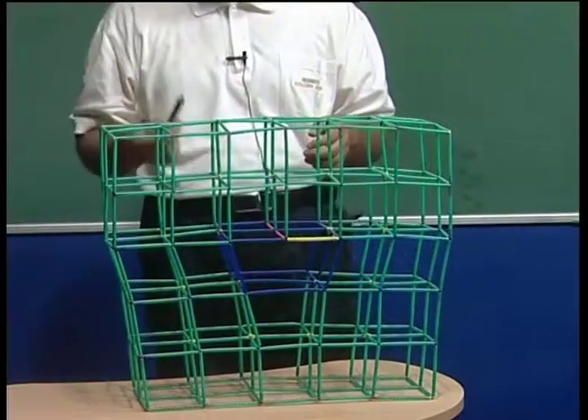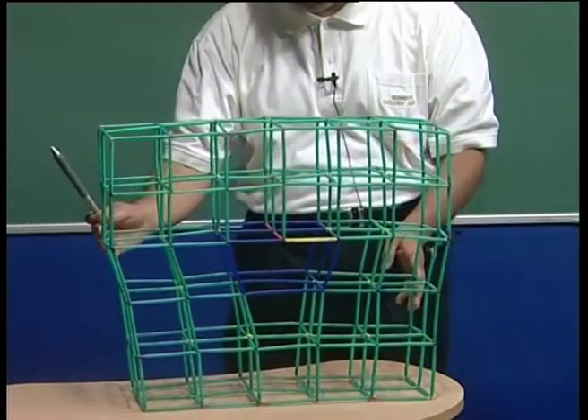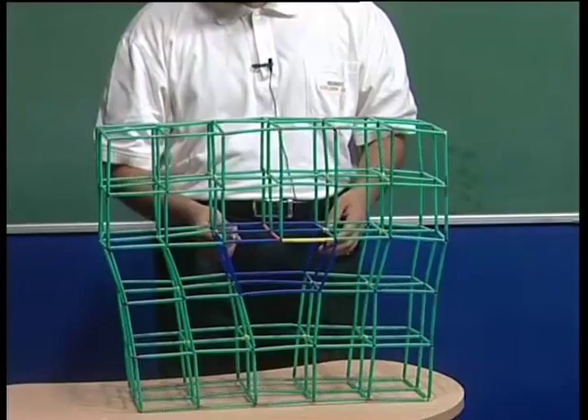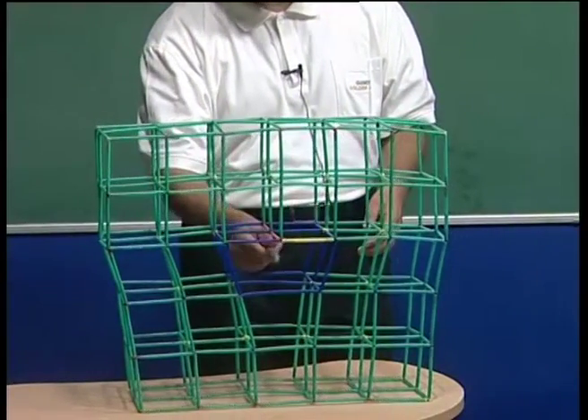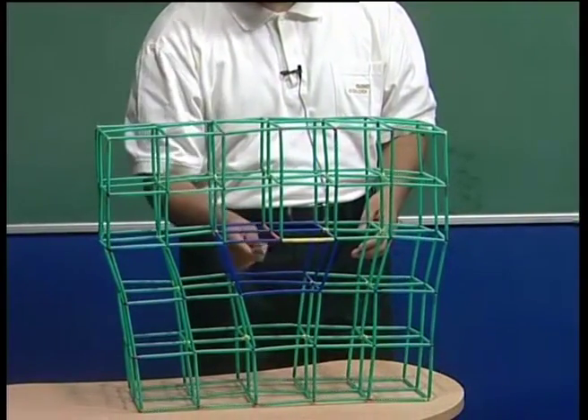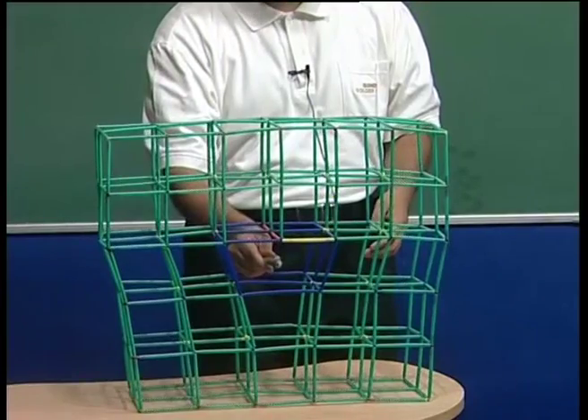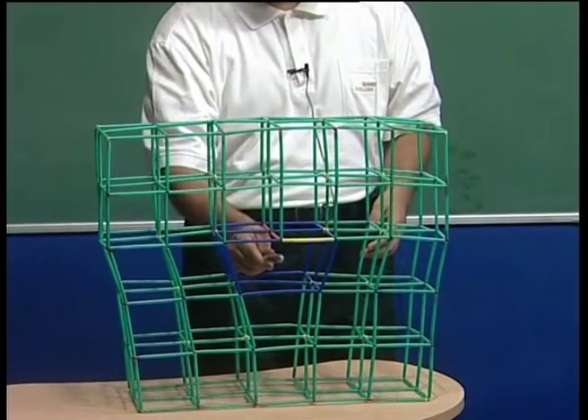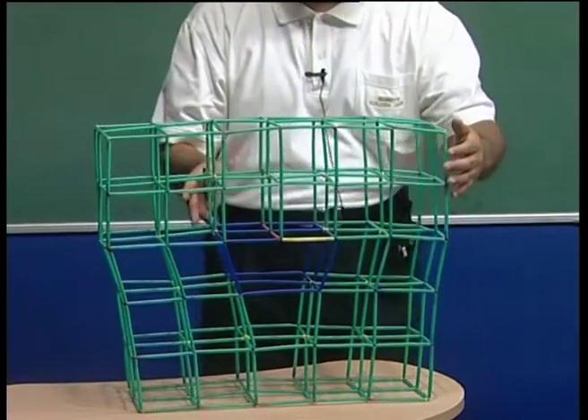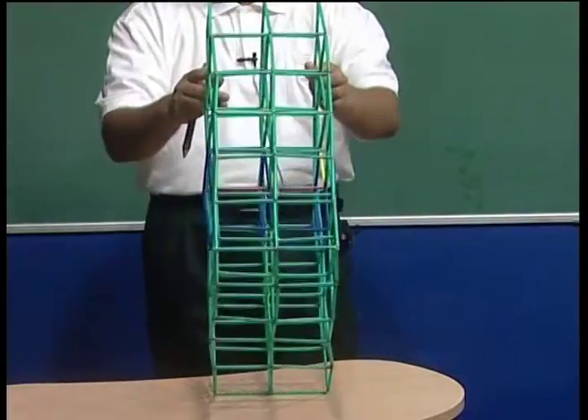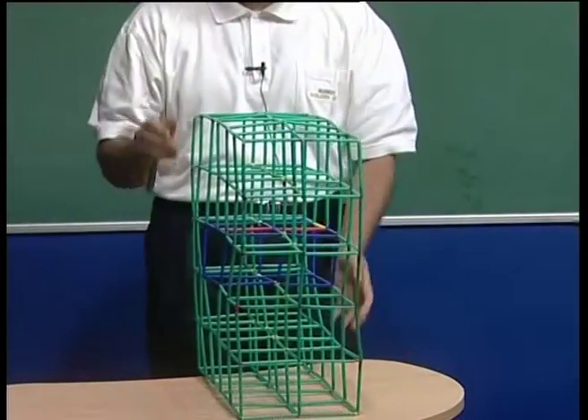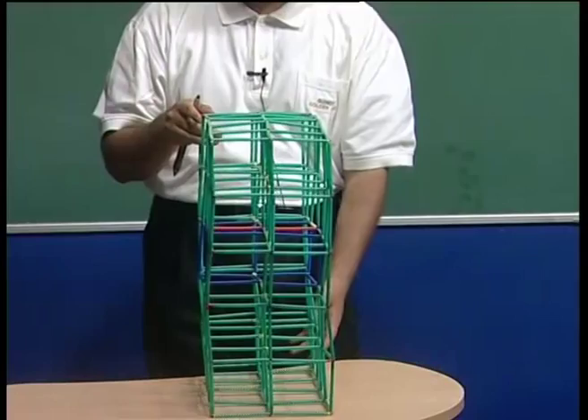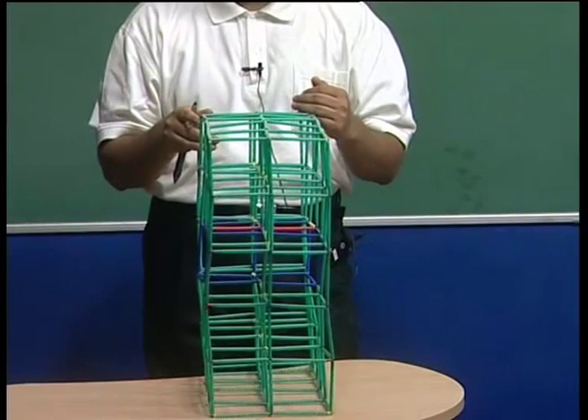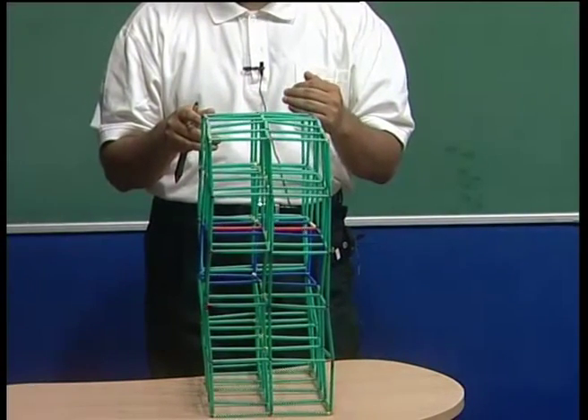Now we can actually draw, for instance, a vector like this, which we can call the Burgers vector, but typically this has to be drawn far away from the dislocation line. Now the dislocation line itself is the line which is here, which is between the missing and the extra half plane of atoms. Now what happens if I look at this crystal from sideways? Sideways we notice that the crystal nearly looks perfect.